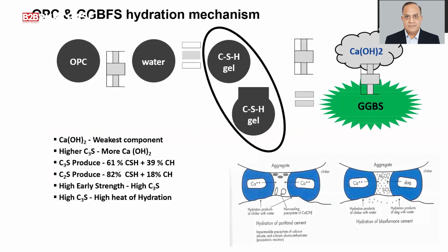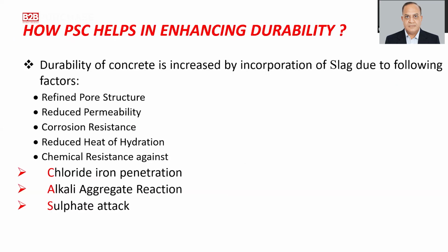And along with that, the CSH gel that is giving compressive strength to the concrete is being doubled compared to OPC or PPC. Because of the higher production of CSH gel, PSC cement is giving higher compressive strength in construction. Along with that, as I told you earlier, chloride, alkali, and sulfate resistance are the most important parameters that PSC cement is giving to the construction, as well as higher impermeable concrete, along with refined pore structure and smooth finishing of white color, which is also good from an aesthetic point of view.